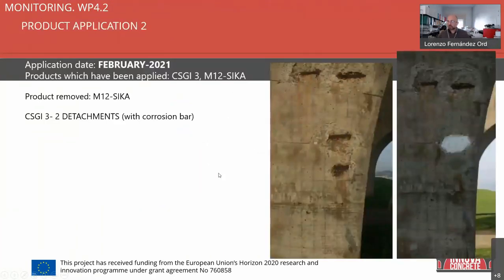Okay, you see, we had problems with the application of the mortar, so we had to do a second application of the mortars, both mortars. You see here on the left is the photo before application, and on the right after. At the bottom is the first application. The top one is the one from Torroja, M12 Sika, and below it is the CSGI 3. Okay, so we applied this, and you see here like a paint, a grid we made in order to measure before application and after application.